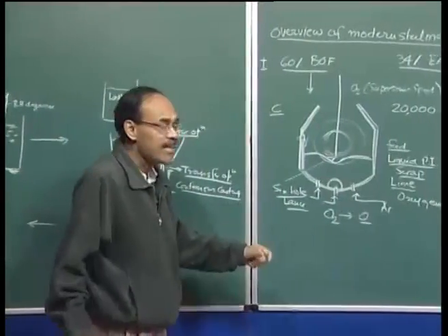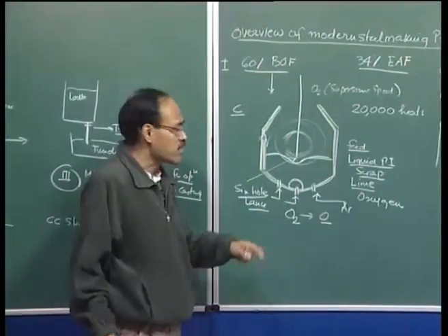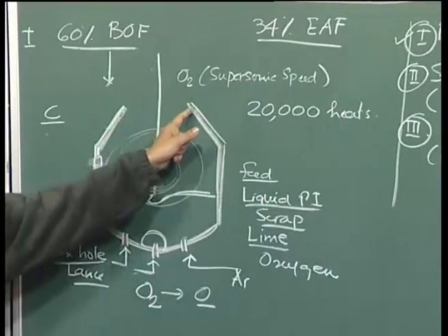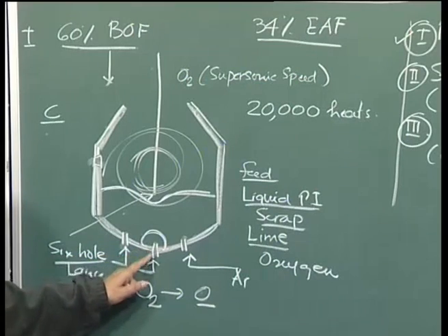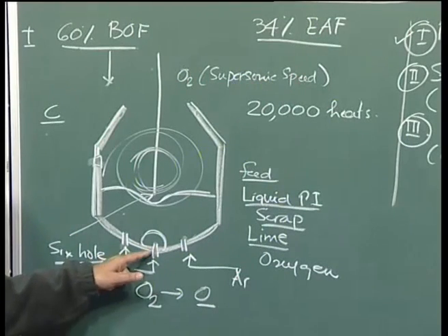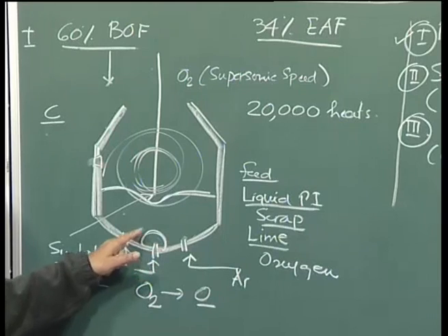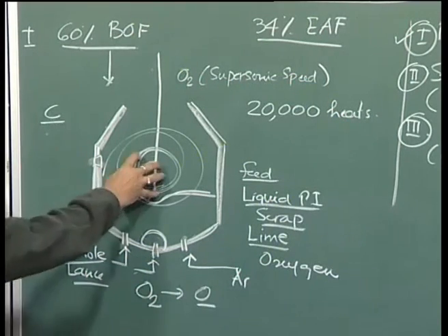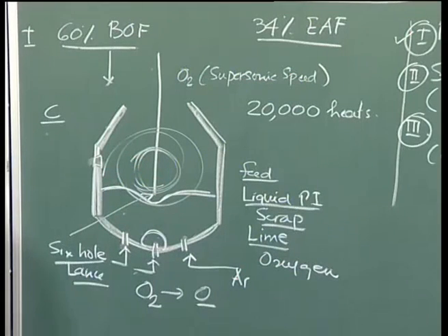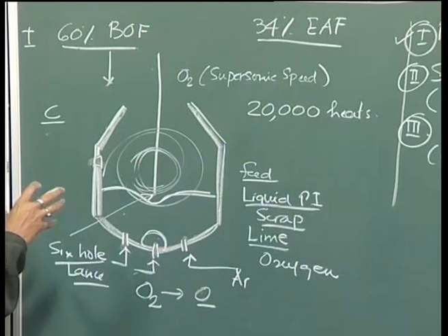There are techniques like slag splashing today to further prolong the life of the lining of the converter. So, coming back to the top blown oxygen process, we have hydrocarbon injection. That hydrocarbon cracks and produces a local endothermic reaction, and that endothermic reaction actually protects the tuyere. So, we have various versions of the steel making processes, mostly LD and combination blown steel making processes are being used, and these are very fast processes, and the main task here is to